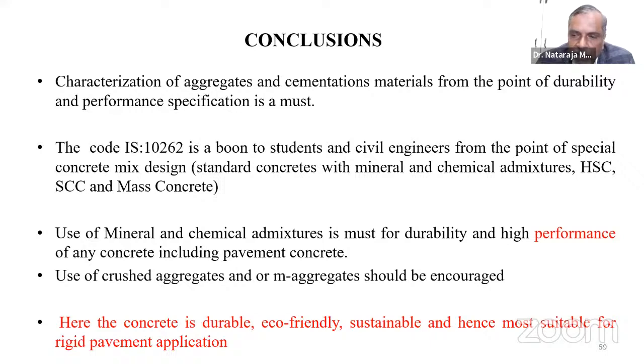If it is less than the size of the aggregate, it is not really going to contribute to the matrix, where I am talking of concrete as a matrix, concrete as a composite. But a smaller length can still contribute to your mortar, but it is not going to contribute to the concrete.